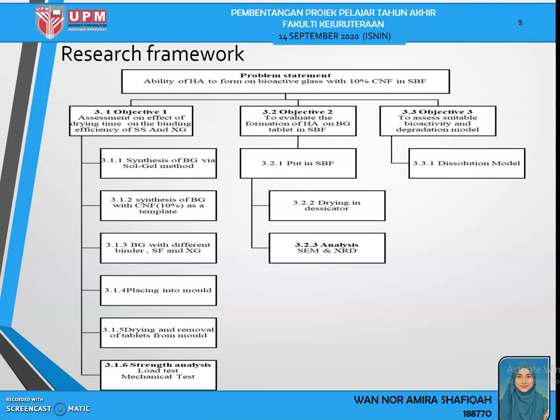So this is the research framework for this project. We have three objectives. For the first one, we synthesize the bioactive glass via the sol-gel method. We use CNF10 as a template. We use different binders such as sago starch and xanthan gum. We place it into the mold, we dry it, and we test it using a load test and a mechanical test. For the second objective, to evaluate the hydroxyapatite formation, we put the tablet in the SBF, we dry it in the desiccator, and we analyze it using SEM and XRD. And for the third objective, to assess the suitable bioactivity and degradation model, we choose the dissolution model.